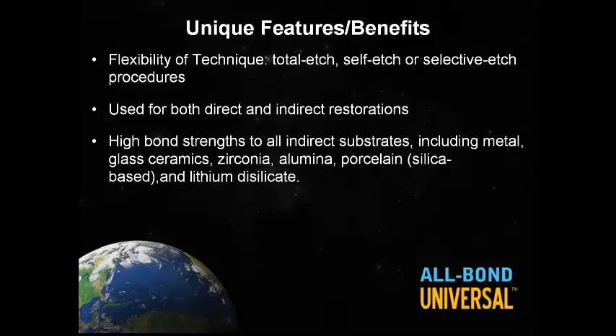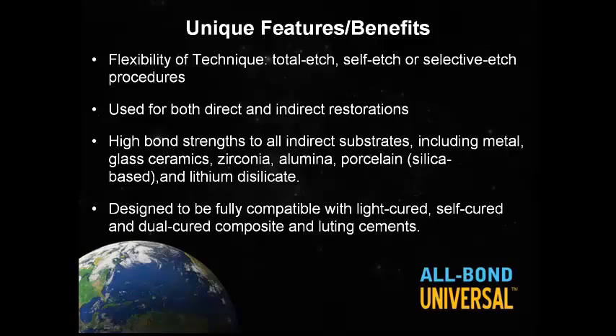As you'll see later in some of the slides and the research on this material, it exhibits very high bond strengths to indirect substrates, including metals, glass, ceramic, zirconia, alumina, porcelain, and the lithium disilicate material that is pretty much one of the other new crazes in dentistry of the recent time. Finally, it's designed to be fully compatible with not only light-cured materials, but self-cured and dual-cure composite and luting cements as well.